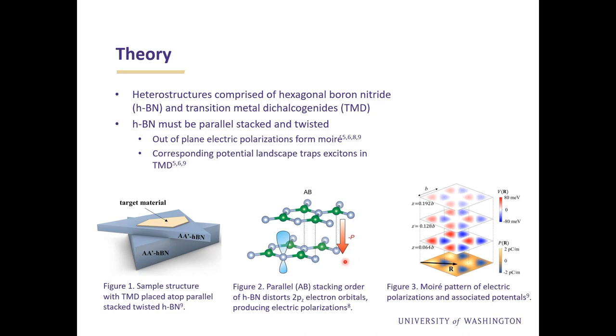If the two layers of HBN are twisted relative to each other, these polarizations form a pattern like this, known as a moiré pattern, where there are specific domains corresponding to polarizations that point into or out of the plane. These polarizations produce an associated potential landscape that contains domains of higher and lower electric potentials, creating an energy landscape in the TMD capable of trapping charged excitons.